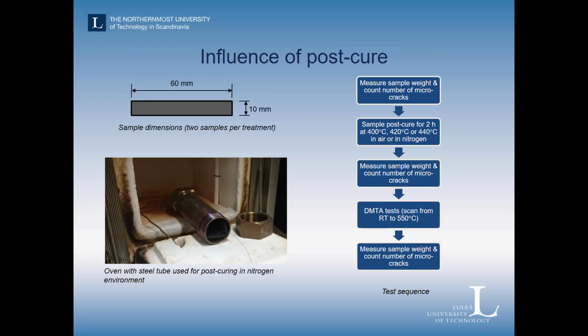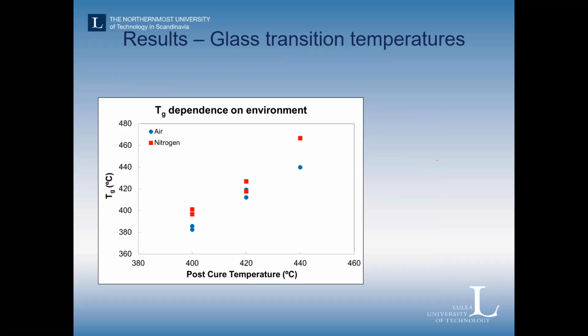We have also looked into the influence of post-curing on these materials. In this case, we have done tests where we characterize the sample weight before and after post-curing for 2 hours at 400, 420, and 440 degrees, and then measure the sample weight and again characterize the number of defects in the format of cracks on the materials.